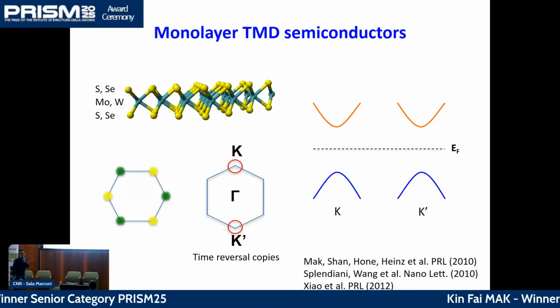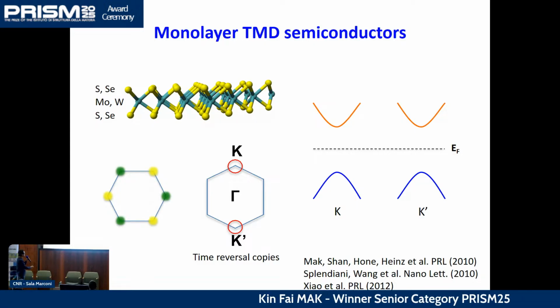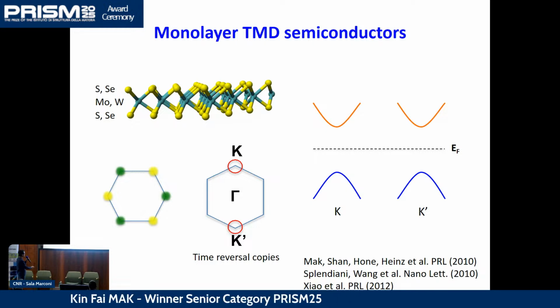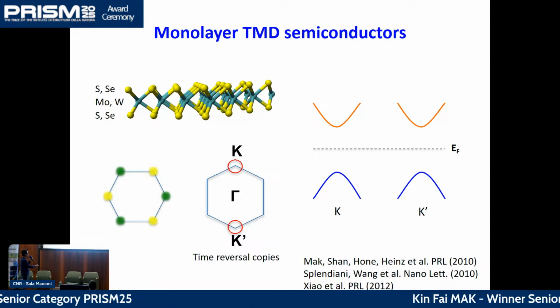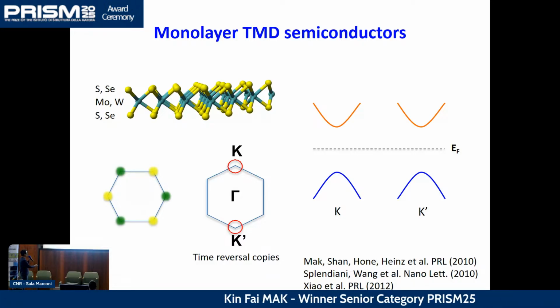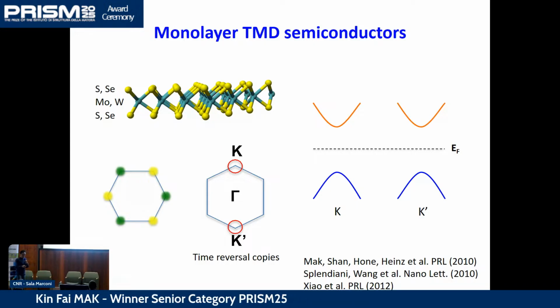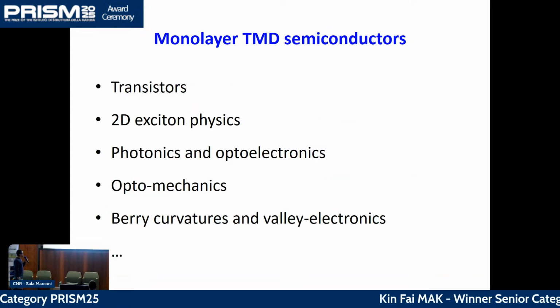So compared to many semiconductors, the electronic states of interest are not located at the gamma point of the Brillouin zone, but rather they are located near the corners of the Brillouin zone. Okay. And the energy gap here, we are talking about 1 to 2 electron volts. And for the intrinsic material, the Fermi level is located in this 1 to 2 electron volt energy gap. All right. So this material is actually quite interesting.